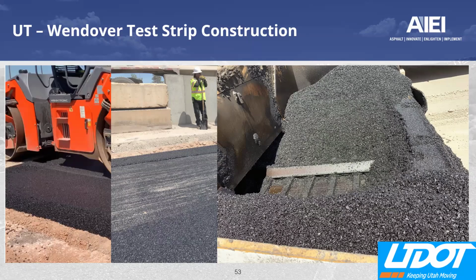But another piece back to the workability is contractors in Utah report to me, and the city of Salt Lake, for example, has had projects. The first project in Montana was an urban project where handwork was necessary as well. The Utah contractors report that handwork with this mix is very similar to what they saw with the 6434 Superpave mix. Recognize that, yeah, this is a stiffer binder, but it's a higher asphalt content and it's a fine graded mix. And so you get some advantages within this system versus the Superpave and some disadvantages. And the upshot is that the contractors reported to be relatively similar.